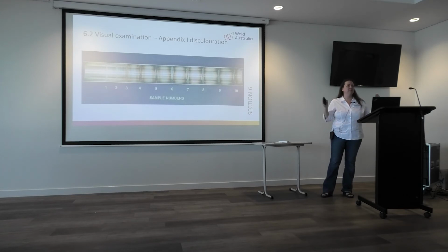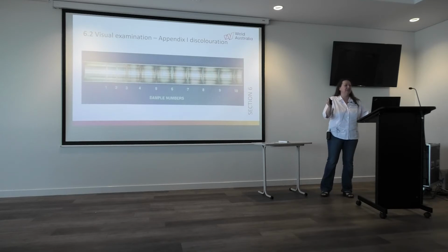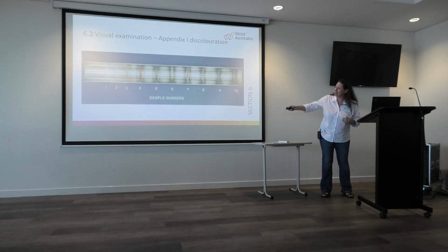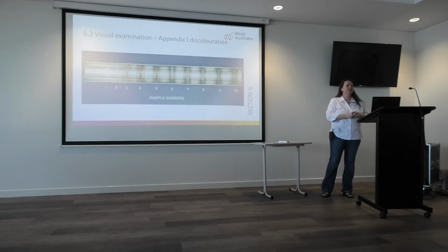So either you put in the effort to have backing gas and you remove all the residual or as much of the oxygen as possible, and you get to that level of cleanliness, or you have to work some way on how to pickle and passivate. And both aspects have their challenges.